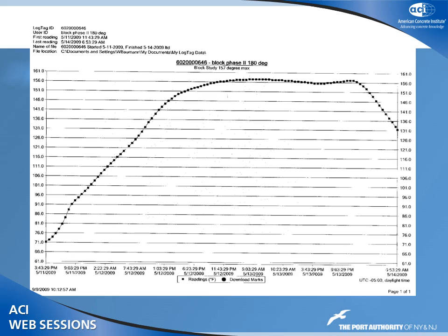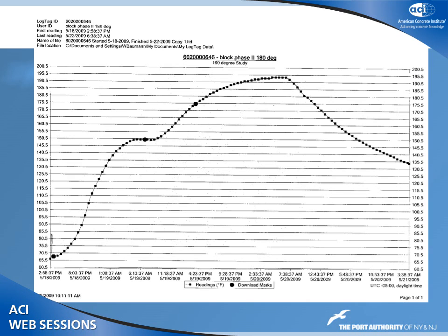Again, we tried to mimic what we had in the field. In the field, the mix produced about 16,000, and same here, about 16,000. The 190 was about the same, although the cores were a little lower. And that's the temperature profile for the 190. Again, we didn't get there for 2 days.